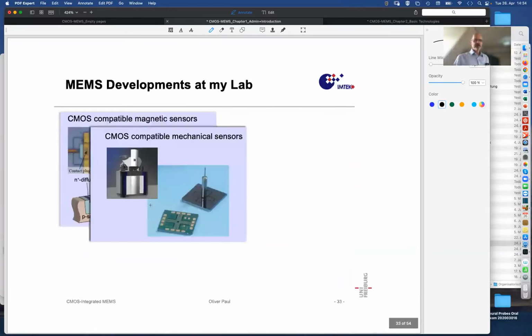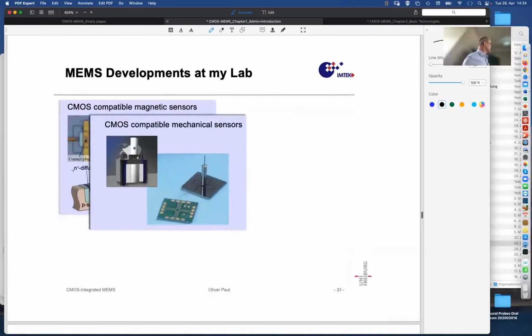So I'll skip that. Then here you see an example of a tactile sensor. This tactile instrument has a little tip. The chip is 6 by 6 millimeters, and it is a micro machine structure actually, so a cross bridge. And so whenever this tip contacts a surface while scanning a surface, you detect that by an ever so tiny displacement of the structure, deformation of the structure, and that deformation is measured using piezoresistive sensors.